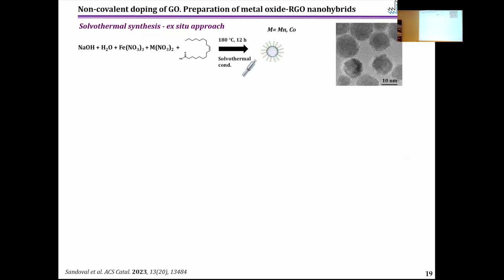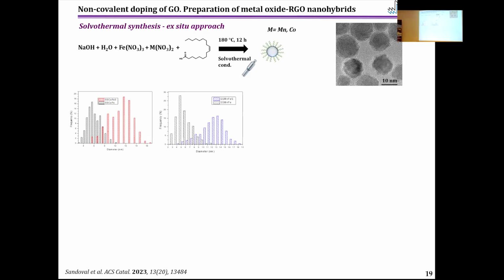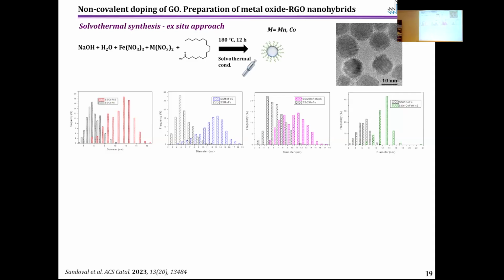So the protocol is fast, it's simple, it's useful, but we have poor control of size. So taking this into account, I have developed a solvothermal synthesis of these nanoparticles. By a two-step approach, this is an ex situ approach. I prepare oleate functionalized cobalt ferrite nanoparticles, which are very stable, very crystalline, and have a very narrow size distribution. Another advantage of this two-step protocol is that we can tune the properties of these nanoparticles before attaching them onto the surface of graphene oxide.